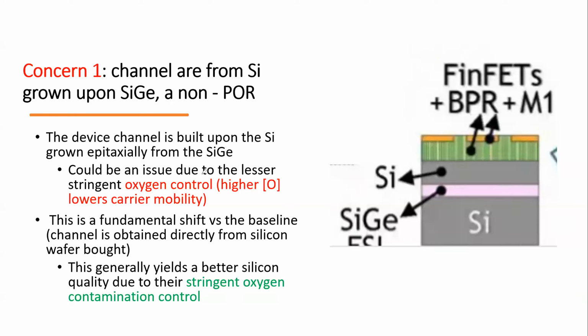You see, the chamber that you use to grow SiGe may have different oxygen, and you don't want oxygen because high oxygen will lower your carrier mobility. It's a contamination. You need very stringent oxygen control. And the wafer you bought from MEMC or somebody else or SEH, the oxygen level in the silicon is very, very low. And here in your epi tool, it's not that low, to be frank. They try to make it low, but it's not that easy. It's still higher than the silicon in the incoming wafers you bought from MEMC or SEH, because they have much more stringent oxygen contamination control.